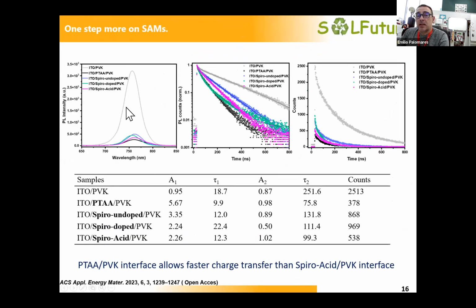This is on photophysics. I'm sure people from James Durrant's group will love that. We still have arguments about what this quenching of the luminescence of the perovskite is due to when you have the SAMs. Some people believe, and I agree with them, that having the SAMs on the ITO before making the perovskite layer makes a difference in the way that the perovskite grows.